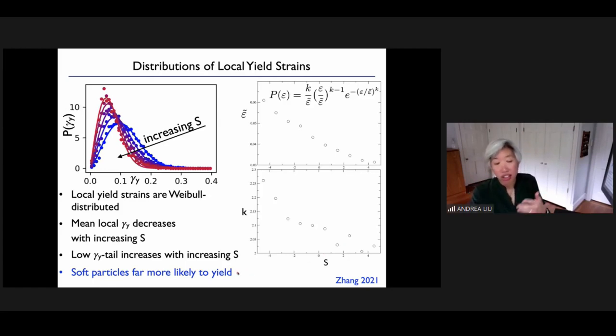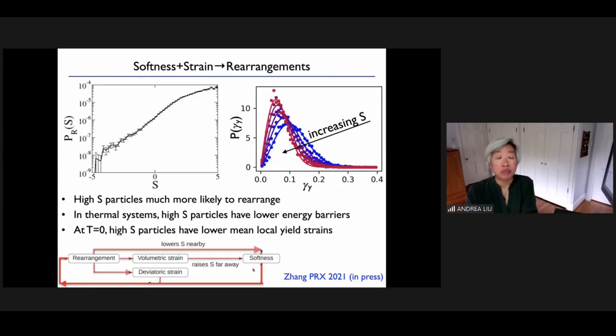So altogether, this tells you that the soft particles are much more likely to yield, which is something that we expected should be true, given that we could predict so well the probability of rearranging. So in thermal systems, we found that high softness particles have lower energy barriers. In these athermal systems, we find that high softness particles have lower mean local yield strains. All right, so that sort of completes the model. It's the softness that determines the local yield strain, and then the deviatoric strain can push the system over the edge to cause a rearrangement.